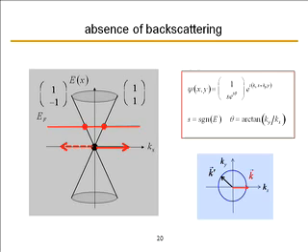Now, it's not quite suppressed to the extent that it is in a carbon nanotube, because these are two-dimensional. So the perfect suppression only occurs for exact backscattering. But when you average over all of the angles, it ends up suppressing the overall average scattering rate. So when you calculate scattering rates for graphene, for acoustic phonon scattering or whatever, you'll get smaller answers than you would with the same perturbing potential in silicon, say. So it's part of the reason that you get higher mobilities.